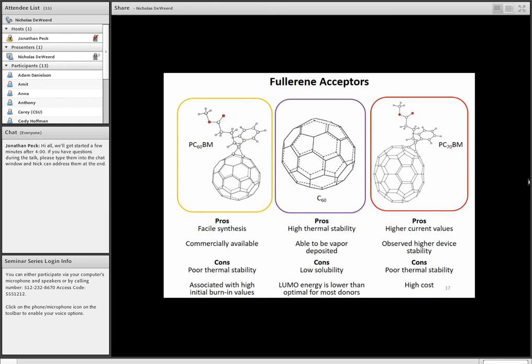If you want to think about it in terms of statistics, when you generate C60 and C70 in that arc synthesis, C60 would be 80%, and C70 would be 20%, and any residual percentage would be left over higher fullerenes, usually sub 1%.